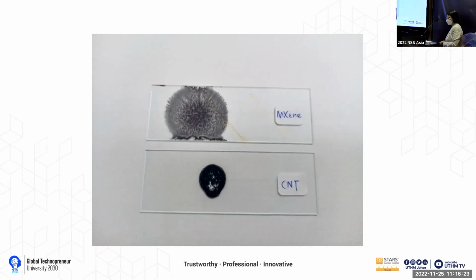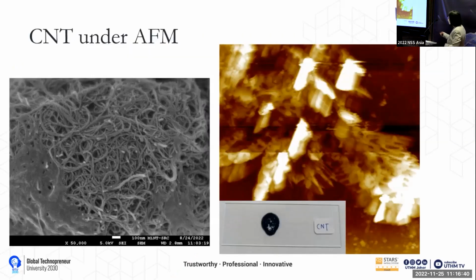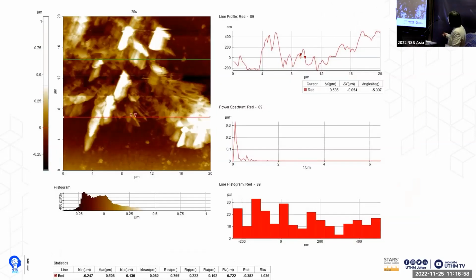Okay. We also try to challenge the system, to see whether it can scan particles or not. Right. So this is MXene, a new material, titanium carbide, prepared with hydrofluoric acid delamination. All right. And also this is the carbon nanotube, just simply cast on a glass slide. All right. So carbon nanotube under AFM is not so good, maybe because our tip radius is too large. Maybe. So we are not able to image the nanomaterial, but however, we are still able to see some structural changes here. All right, so this is the line profile of that carbon nanotube.